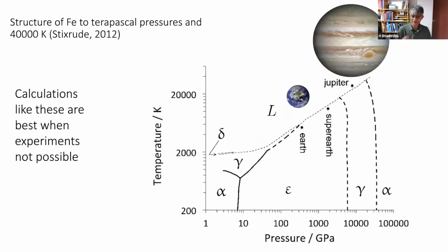Okay, so that's pure iron, but there's more to it. We are now interested in planets which are much bigger than the Earth, 10 times bigger than the Earth, the so-called exoplanets. And the core of the Earth contains solid iron, which probably is in the form of the hexagonal close-packed variant. And this has been studied by looking at longitudinal and transverse pressure waves traveling through the core. But when we go to even higher pressures, the first principles calculations indicate that we should revert to austenite at very high pressures, and then to a slightly tetragonal form of ferrite, only slightly tetragonal. Of course, these have not been experimentally verified, although we have some information about the state of the iron in the middle of the Earth.